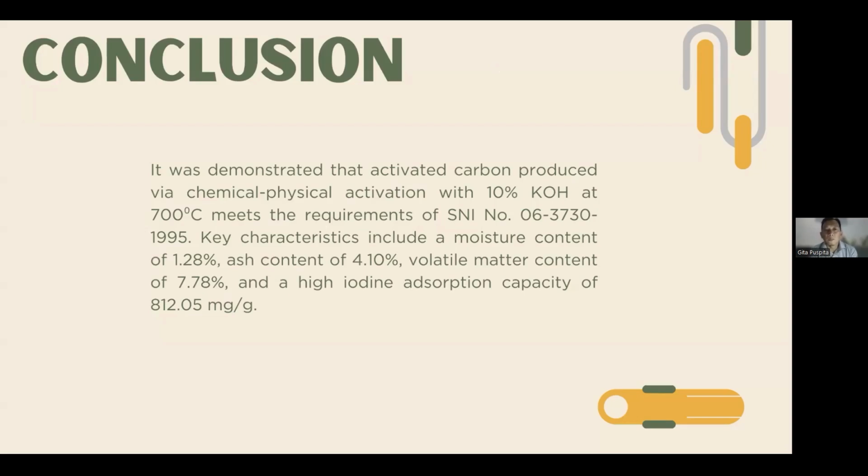It was demonstrated that activated carbon produced via chemical physical activation with 10% potassium hydroxide at 700 degrees Celsius meets the requirement of Indonesian Industrial Standard number 06-3730-1995. The key characteristics include a moisture content of 1.28%, ash content of 4.10%, volatile matter content of 7.78%, and a high iodine absorption capacity of 812.05 milligram per gram. So I think that's all from me.